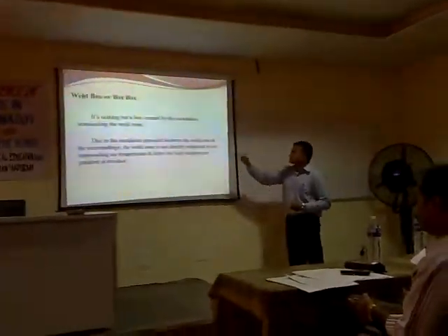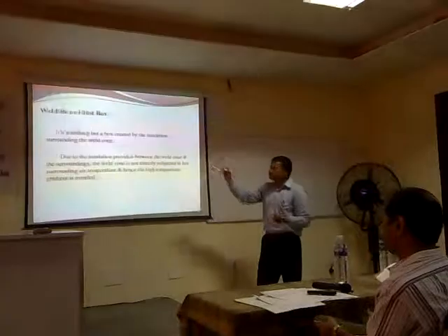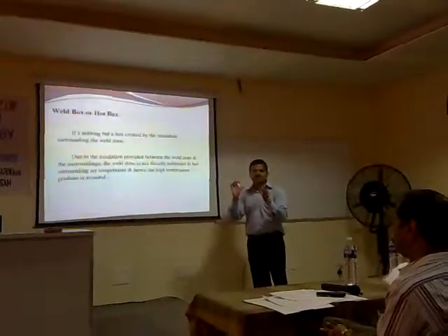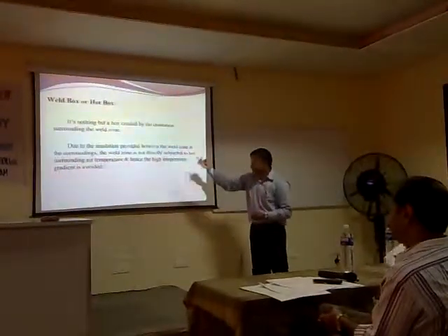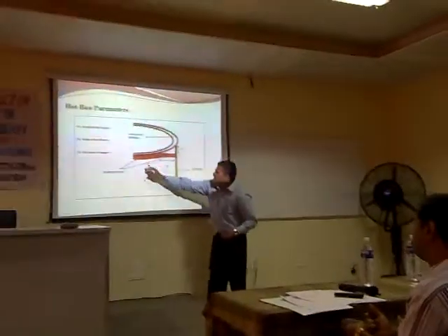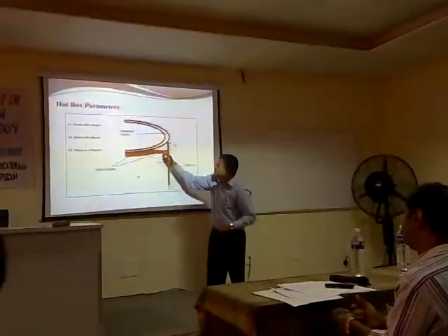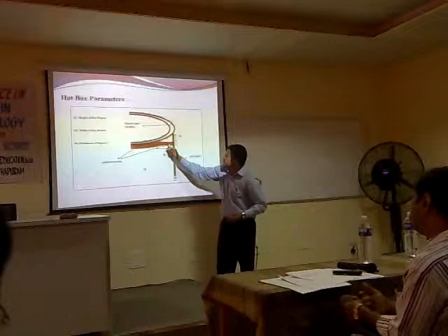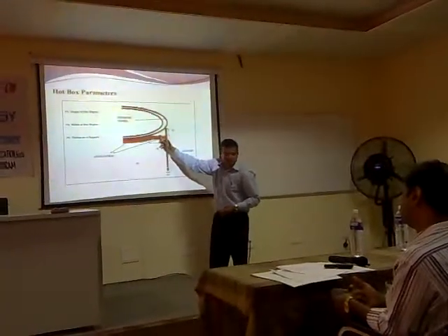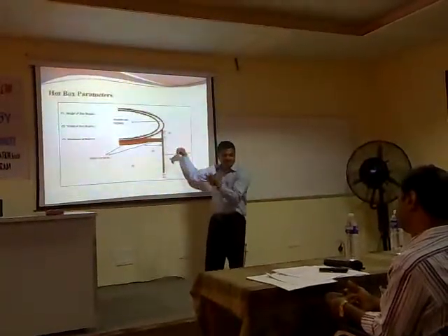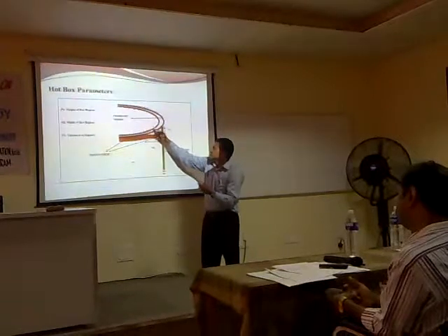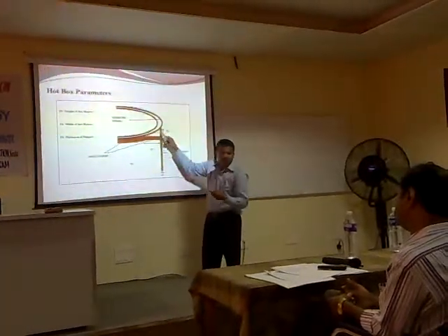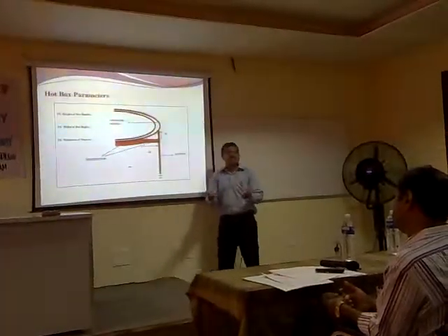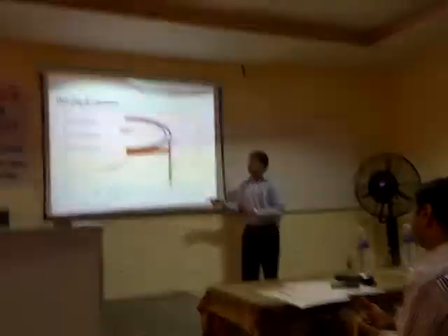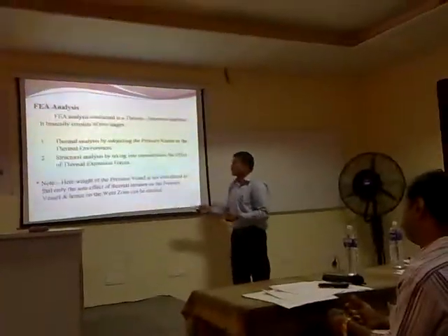Next. So what I am introducing here is the concept of the weld box or hot box. The hot box is nothing but an insulation kind of ring provided like over here. Now, if we consider this as the insulation, then heat flowing across this section will be restricted in this zone, due to which the temperature in that zone will increase. And as the temperature increases, the temperature difference across this weld zone will reduce, and hence the thermal stresses and all these consequences will be avoided.